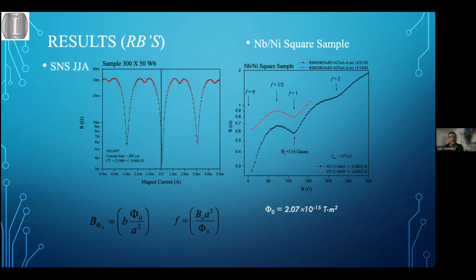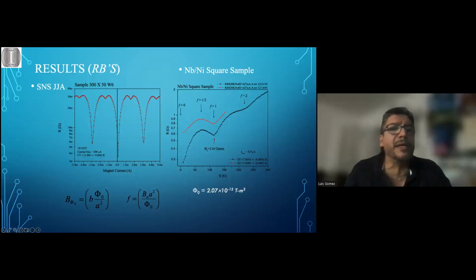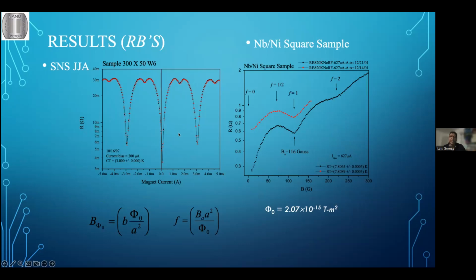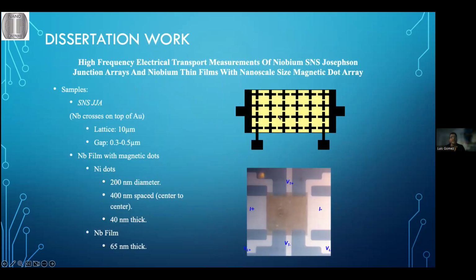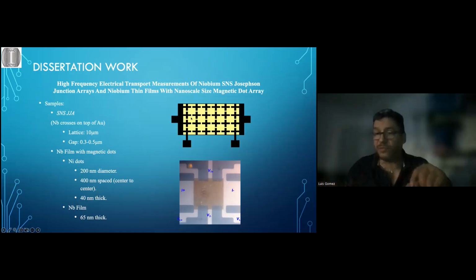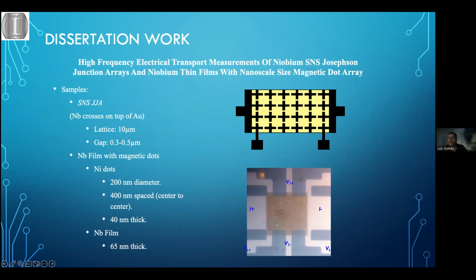And this last measurement is with a magnetic field. As you apply a perpendicular magnetic field to the sample and measure the resistance, the resistance as a function of the applied magnetic field also has these dips. Basically, if you look at the system here, you have four Josephson junctions arranged in this fashion. This creates what's called a SQUID.